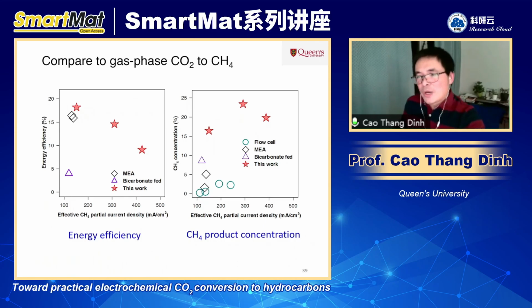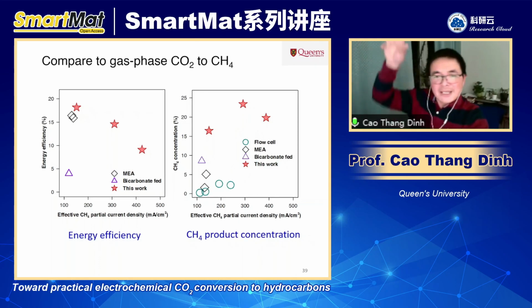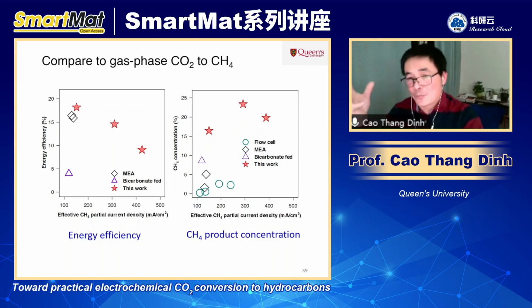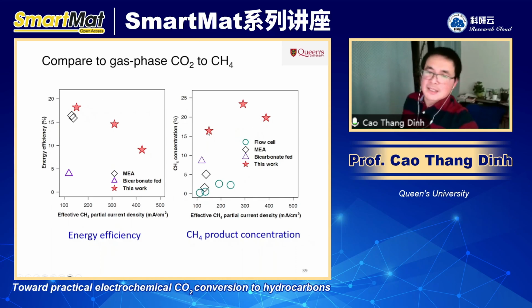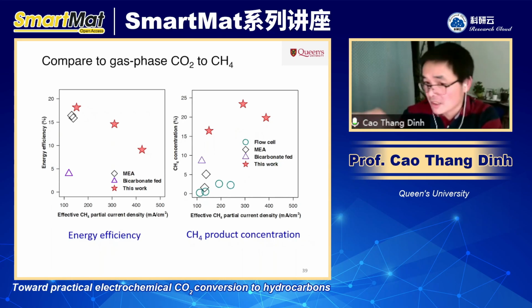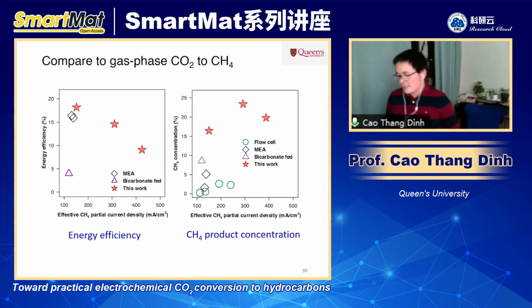And another interesting point, which I like about the bicarbonate conversion system, is the product concentration. Because we feed in the liquid, and then you make the methane, which is a gas, the methane is automatically separated from the liquid, so you have pretty good separation. And then you have a pretty good methane concentration in your system. And that is reflected in this graph on the right-hand side. In our system, we have methane concentration from 15 to 20-something percent, while most of the previous work on the gas phase has less than 10% methane. And why is this important? Because the separation cost of the methane will depend on the concentration of the methane in the stream, right? So that's another good thing.